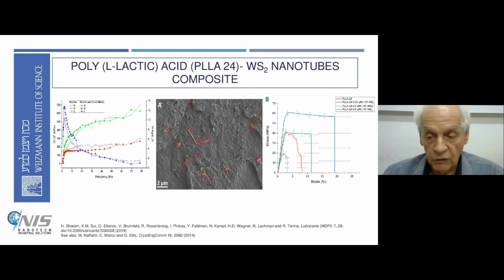You see that the neat polymer, PLLA, is very weak. When we add nanotubes, we can gradually make it very robust. Not only does it become strong, but if you integrate—take the area under the curve—that represents the force required to break the polymer. Comparing that area to this, or even to that, you see that adding a very small amount of these nanotubes reinforces the polymer dramatically.